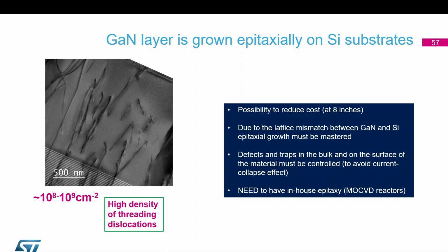Yeah, of course, whatever you do in your epitaxy, so the silicon substrate is here, you have a lot of multilayers and other stuff which are used to manage the stress that you have and to reduce whatever gets to the surface. Still, you have some threading dislocations going up and reaching the active part of your device. So once again, you need to have internal work, because you cannot just buy epitaxy from outside. If you buy from outside, you cannot control your destiny in terms of these defects. And especially, it's been proven by several groups, including ours, that in this kind of device you have a continuous loop between the device structure and the epi. When you make a true optimization step, you optimize both the device structure and, accordingly, the epi. You cannot decouple the two, so you need to control both. Otherwise, you lose a very good knob in your design capability.